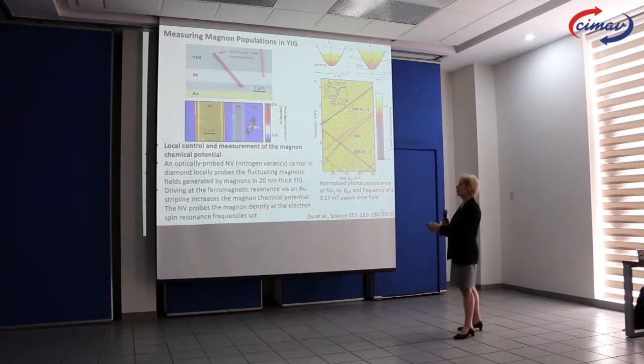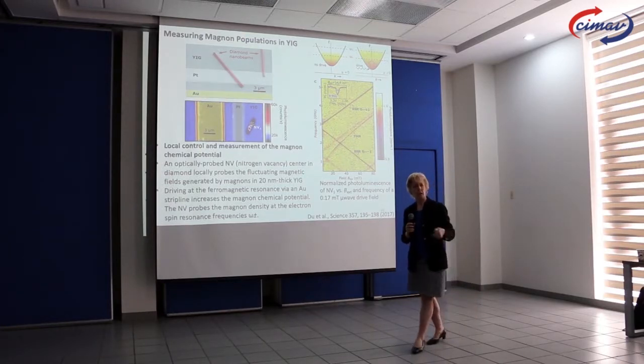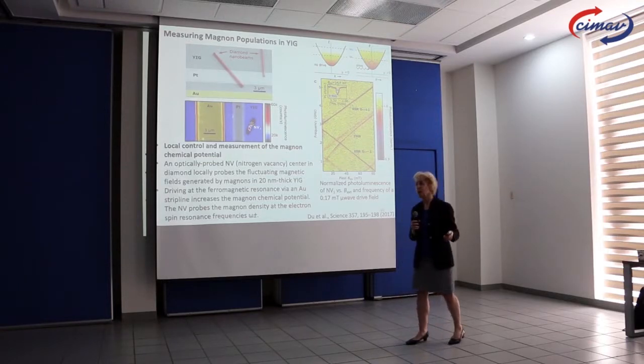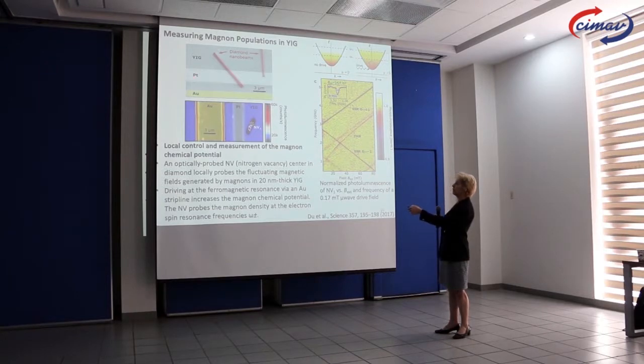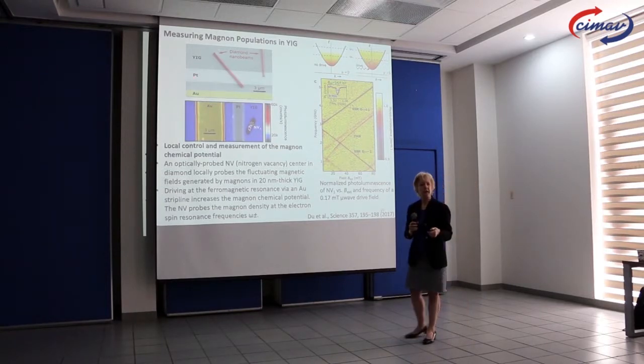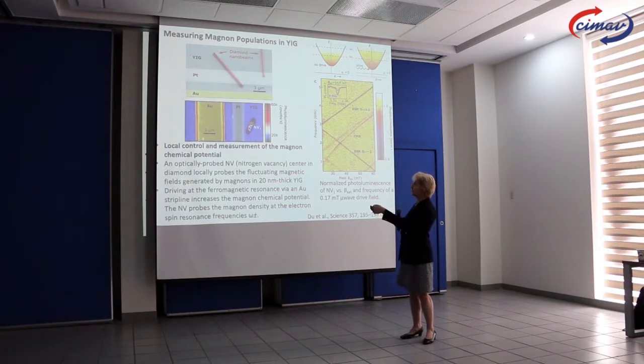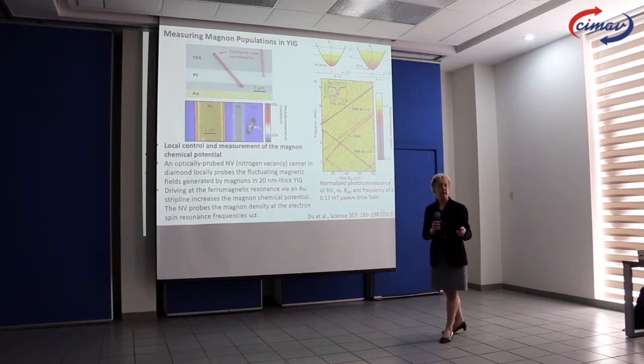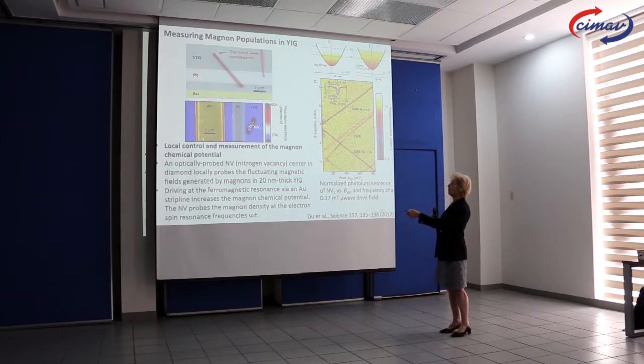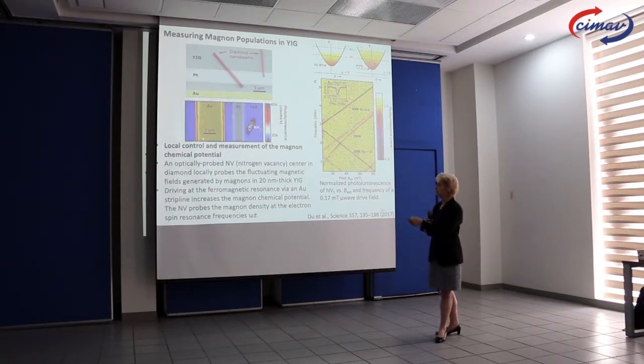Now, one thing I should mention about these magnon generation is, so far I showed you that if we have a gold wire, we can use an RF signal, coplanar waveguide geometry, and excite these spin waves. We can also do it another way, and that's by using a platinum wire. And what happens here is that the platinum will excite magnons in the YIG by a completely different phenomenon that's nothing to do with RF magnetic fields. It's actually due to a spin current which is injected into the garnet. And I'm going to talk about that a little bit later on. But for now, let me just say that this is an alternative way of exciting spin waves in a magnetic material.